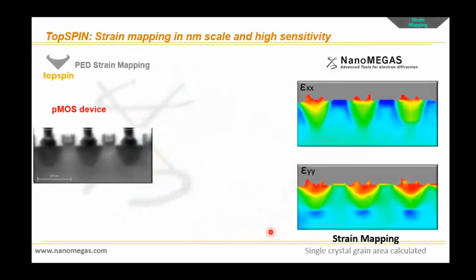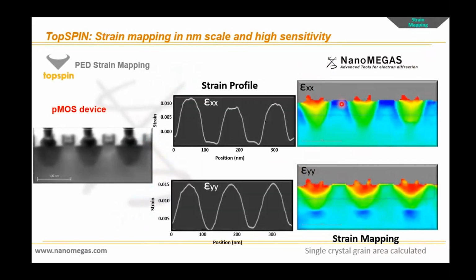Whatever you see, this red color means tensile strain and blue color means compressive strain. You can, of course, have some strain profiles. And the important thing here is that we can go to a spatial resolution down to 1 to 5 nanometers. And we can have strain sensitivity that can go down to 0.02% of strain detection.